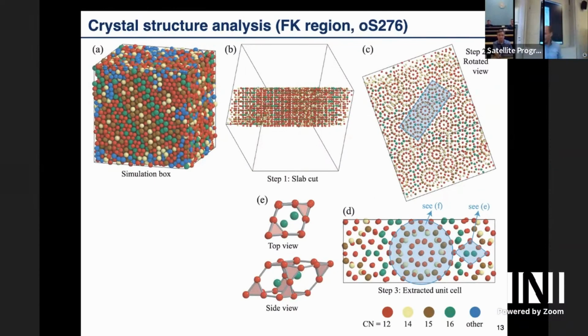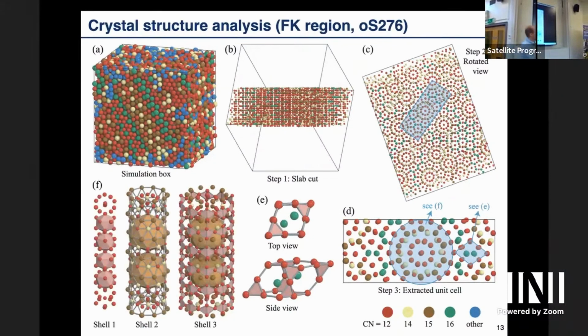It's a little bit like in FCC and HCP, you can either have an ABC stacking or an ABAB stacking, and then you get FCC or HCP. Just like that, in Laves phases you have these different Laves phases, and they're actually quite related to FCC, BCC. And then you have here these center ones, which are these very complicated channels. And yeah, they have different shells.